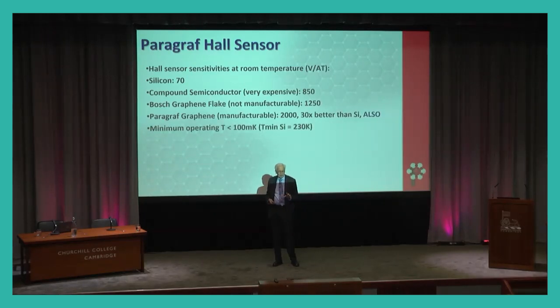So it can work at cryogenic temperatures. It can work at less than 100 millikelvin. That's the lowest temperature we've tried it. So I'm sure it will work lower still. The minimum temperature a silicon Hall sensor can operate at is about 230 Kelvin, because I think the carriers get frozen out at lower temperatures. So we have a sensor, well, really a cryogenic sensor.